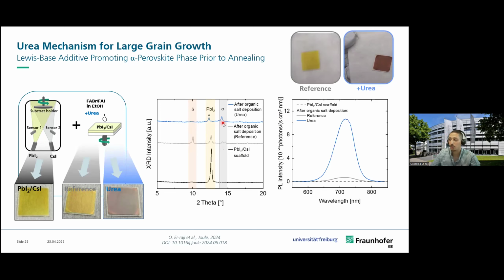Now, what impact did these simultaneous changes have on the device? So again, we measured suns-Voc, and here we saw that the series resistance was reduced for the device with urea because of the large grain growth and the improved conversion. And in terms of mobile ion density, we observed that devices with urea had a lower mobile ion density. And in solar cells, we observe that there is no more light soaking effect present. And in terms of efficiency improvement, here you can see the device architecture, also the VOC, fill factor, JSC, and efficiency. And both in forward and reverse scans, you can see that the efficiency was improved by up to 2% absolute, mainly due to improvements in VOC and in fill factor.